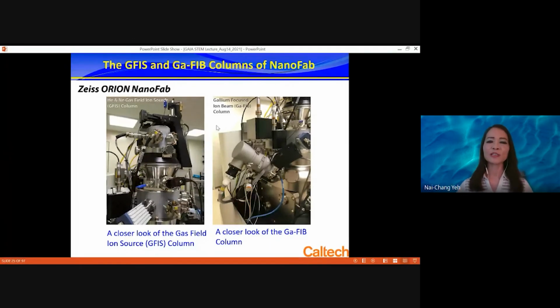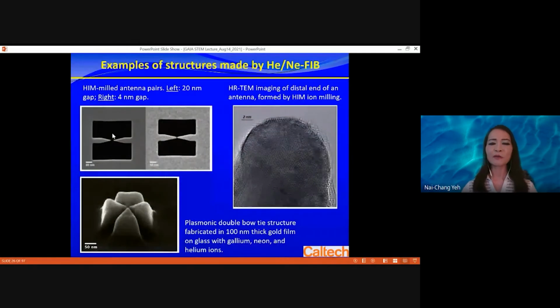That means you can decide what you want to do. If you want to remove a lot of material, you use the gallium beam. If you want very fine resolution and low damage, then you use the helium-neon ion beam. So here are pictures showing that we can use these three beam combinations to make very, very fine structures.